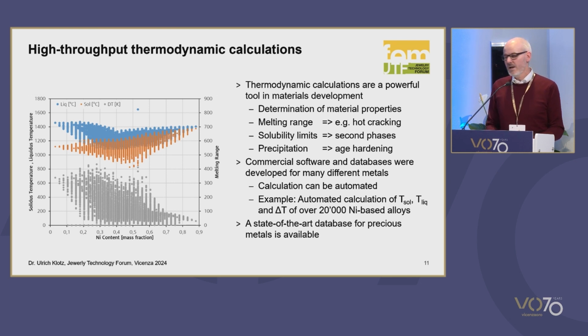And so I used the high throughput calculation technique and calculated 20,000 alloy compositions. And this plot is showing the results. So you see that the solidus, the liquidus temperature, and the melting range are varying in a quite wide range. And with a set of filters, we narrowed down these 20,000 alloys to about 10 alloys that we found interesting